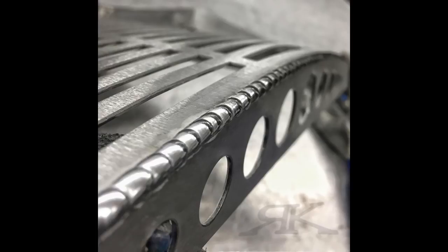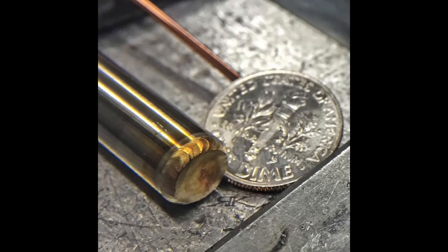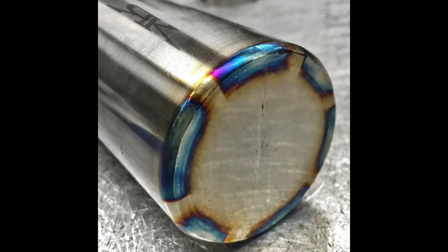Yeah, thanks for having me on here. So the active gas welding, instead of being a total inert gas like running straight argon, it has oxygen in this particular gas and a small amount of nitrogen and hydrogen. Those gases make the aluminum react differently than in a total inert environment. With the nitrogen and hydrogen, they'll help the arc burn hotter. It can eliminate the preheating, and it'll allow your arc to start out really stable, burn more fluid off the start. And then it has the oxygen, so when aluminum is exposed to the oxygen, it hardens the weld faster than when it's totally encased in that inert environment.